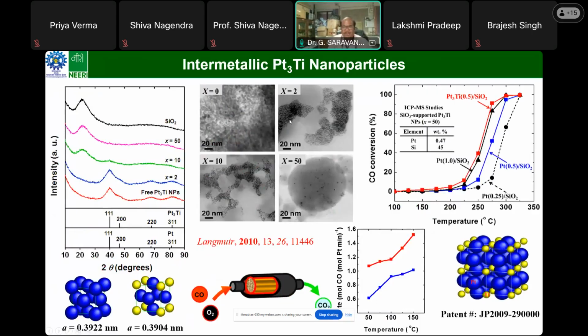carbon monoxide oxidation. Here we have developed a catalyst using silica as a support, and with increasing of the silica support, we have very finely dispersed nanoparticles. The particle size is roughly 2 nanometers, and this is highly homogeneously dispersed across the support. So this is the typical catalytic performance, and this one is 0.5 platinum loading. At the same loading weight, the intermetallic phase of PtTi shows much higher activity than the commercial or reference platinum.